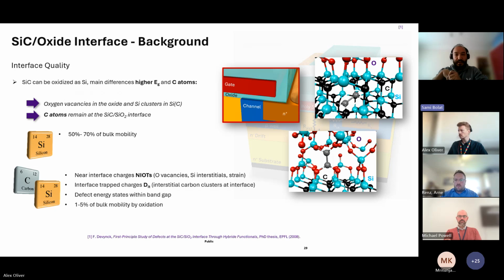We have the carbon clustering that is creating several defect energy states within the bandgap. And as a result, even today, in the state-of-the-art devices in the market, we have 1 to 5% of bulk mobility by oxidation. Very recently at the ICSCRM conference, we heard from an industrially renowned expert, Peter Moens, that there should be a way to improve this mobility by an order of magnitude at least, so that we can talk about reaching the limits of silicon carbide technology today.